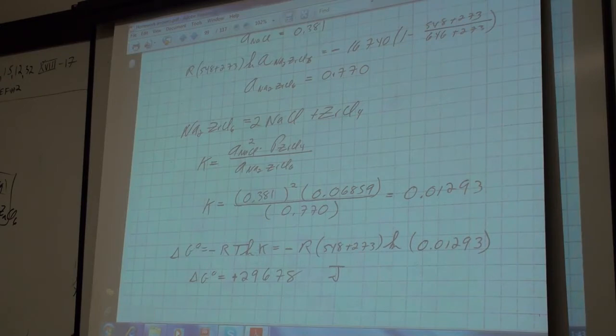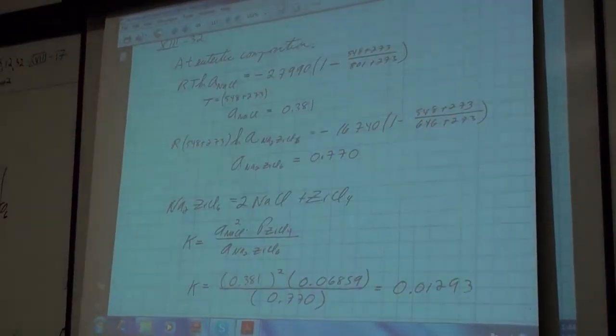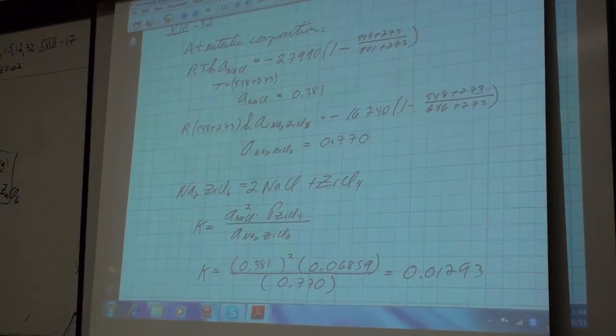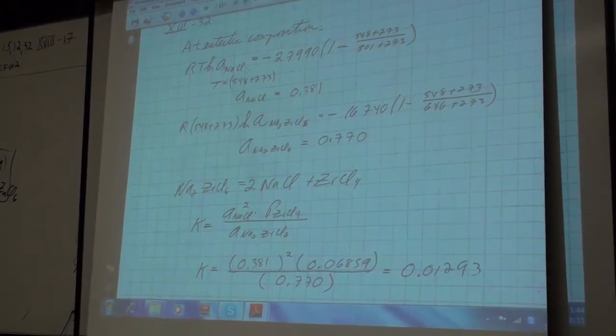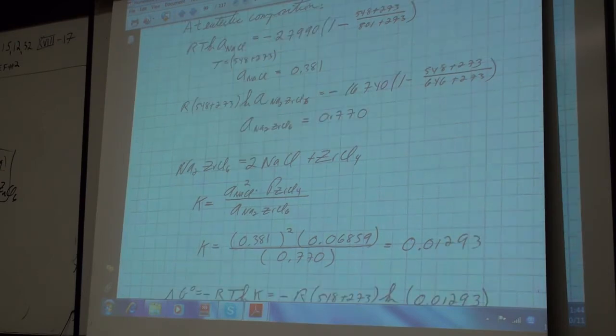And now to get the equilibrium constant, I need to know the activities of sodium chloride and Na2ZrCl6 at some composition where both activities are known. Okay. So I can get that, of course, from the eutectic composition, as we did at the eutectic composition. This is the liquidus of sodium chloride. Same thing, RT log activity of sodium chloride is the heat of fusion times 1 minus T over T fusion, that's the activity of sodium chloride. Assuming no solid solubility and assuming a heat of fusion independent of temperature. And then for the other liquidus, you do the same thing to get the activity of hexachlorozirconate.